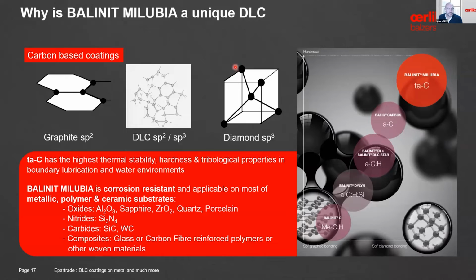But when we look at the properties of this coating, it was really incredible because first, the hardness, the hardness of the coating itself is really, really high, much higher than any other DLC that we can apply at the moment. Well, that was not the main interest. The biggest interest that we found in this coating and this technology is that we could apply the coating on almost everything. Or at least, when I say everything, it is at least a lot of non-conductive substrates that we could not easily coat in the past. So it's true that today with this solution, we can apply the coating on different carbide surfaces, silicon carbide, etc. We can apply the coating on different ceramics, alumina, other parts. We can also even apply the coating on PEEK.